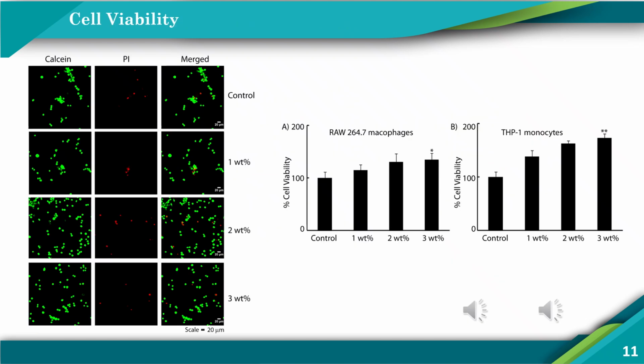Finally, the biological performance. Live-dead staining shows predominantly green fluorescence, which indicates viable cells. This means the hydrogel network is not only mechanically functional but also biologically compatible. So we now have a material that self-assembles, forms structured nanofibers, exhibits strong mechanical properties, shows thixotropic recovery, and supports cell viability. That's the complete structure-function biology connection.